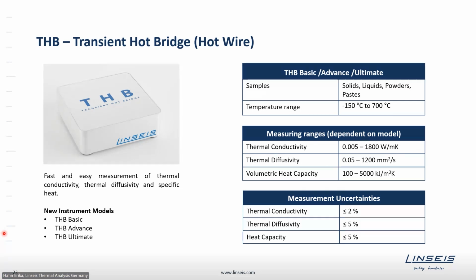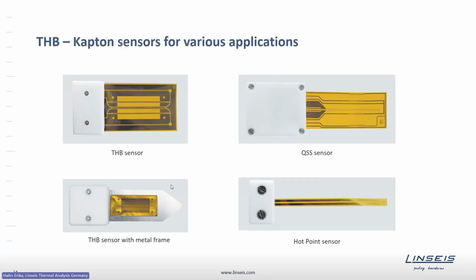As this instrument is based on the hot wire, we need some hot wires. So we have this hot wire built in a sensor, so that the wires are embedded in a Kapton foil, or we have also this high temperature version where these wires are printed on a ceramic substrate. And basically we have here 4 groups of sensors: the THB sensors for low conductive materials, the QSS sensor for the high conductive materials, the THB sensor with a metal frame for powders, pastes, and liquids, and the hot point sensor for very small samples.